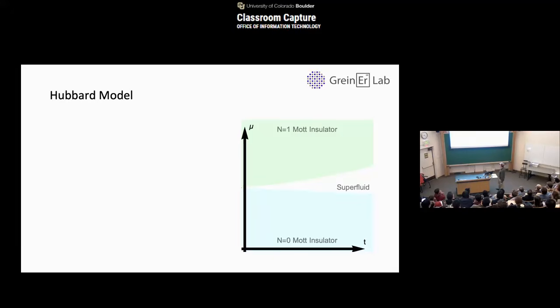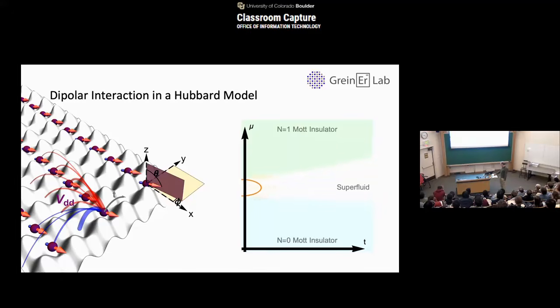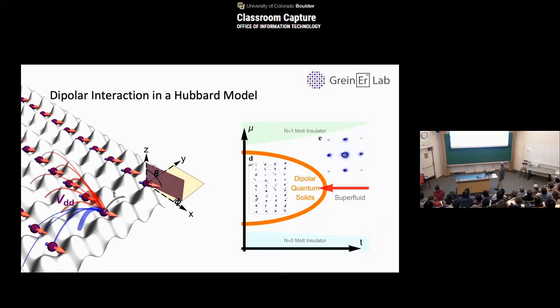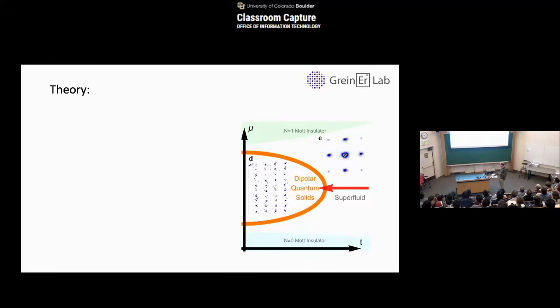So here's a superfluid Mott diagram. This is the chemical potential and the tunneling. And if we come from large tunneling here at half filling, then we follow between the n equals 0 and n equals 1 Mott insulator at half filling into this superfluid. But we can now zoom in here, and at very low tunnelings, all kinds of interesting quantum phases emerge that are caused by these dipolar interactions. And how we prepare it is we start with the superfluid, and then we move into this regime where we expect the quantum solids, and we do a quantum phase transition from the superfluid into the states that you expect if you have dipolar interaction.